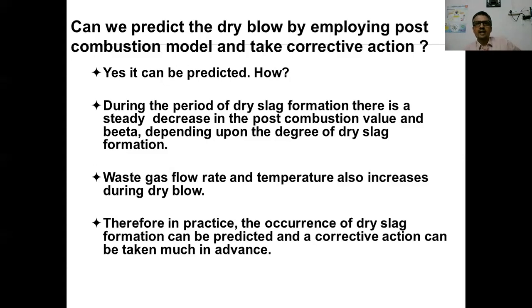So we can predict the dry blow by employing the post-combustion model, and we can take corrective action. How? As we know, during the period of dry slag formation, there is a steady decrease in the post-combustion value, and depending upon that, we can predict the degree of dry slag formation. Other things that can occur are that the waste gas volumetric flow rate and temperature also increase during the dry blow period. Therefore, in practice, the occurrence of dry slag formation can be predicted and corrective action can be taken much in advance with the help of the post-combustion control model.